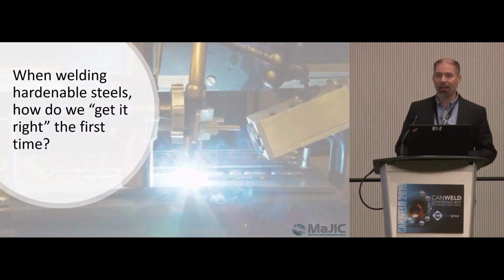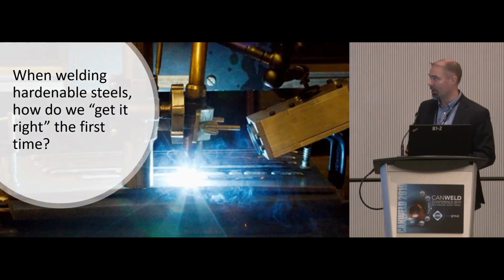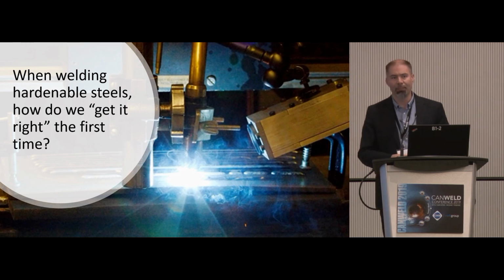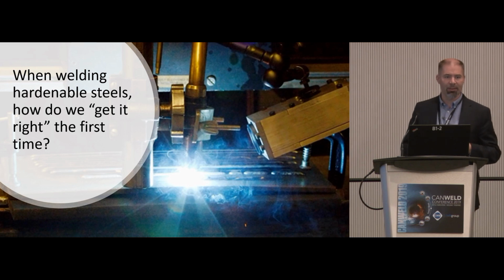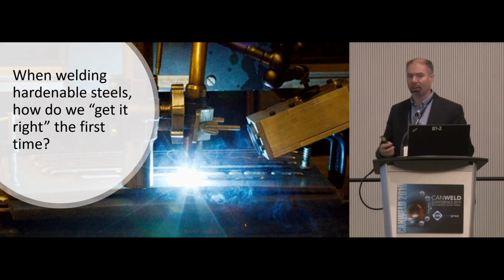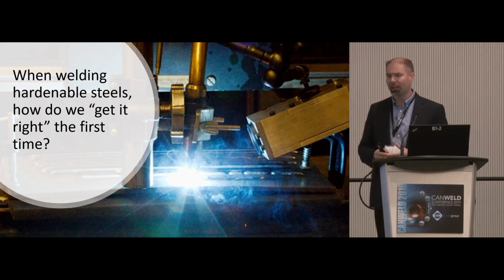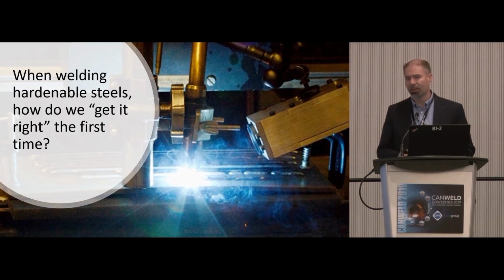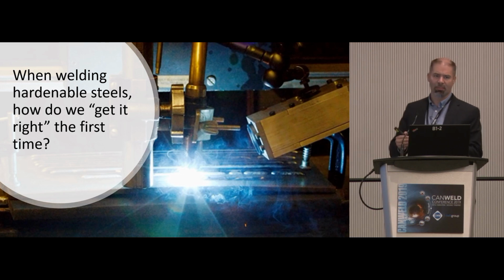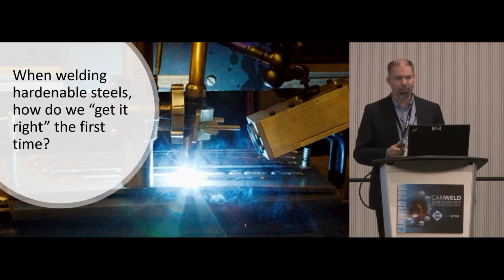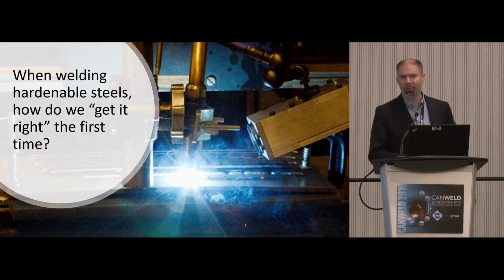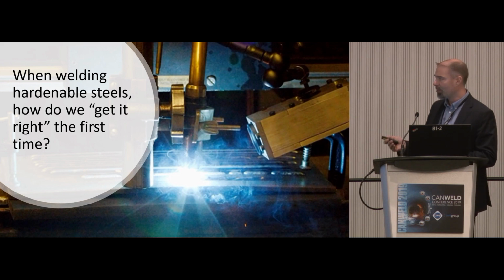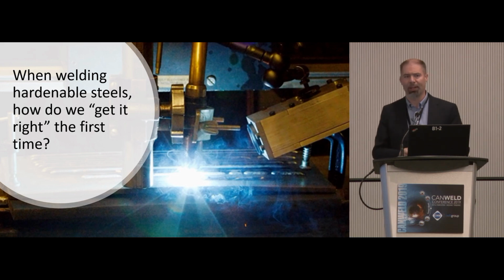So one of the challenges that we have is answering the question of how do we get it right the first time? Welding hardenable steels, as anyone in the welding industry knows, is somewhat challenging. So when I say hardenable steels, I'm generally talking about medium alloy steels with carbon equivalents over 0.6 to 1 and over range. Total carbon content on the steels that we'll look at today, we've targeted around 0.4%. So these are hardenable steels. We do easily get a lot of martensite. But the question is, how do we get it right the first time?